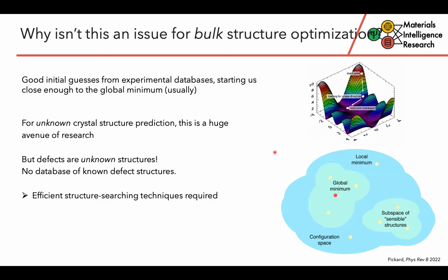I think something that's maybe interesting to note is, well, why is this not an issue for bulk crystal structure optimization? So why is this just something unique to defects? And I would say that, well, generally when we're relaxing a bulk crystal structure, of course, we have a good initial guess of what the structure is from experimental databases, such as the ICSD, which basically starts the gradient optimization close enough to the global minimum that we don't need to worry about this behavior. The thing is, for unknown crystal structure prediction, so predicting the crystal structure of a chemical composition that hasn't actually been made experimentally before, this is indeed a huge avenue of research, a huge scientific problem, and many different approaches have been trialed for that.